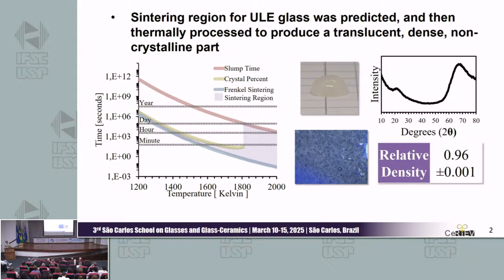The purple highlighted region shows where we have suitable sintering parameters. So at that time and temperature, you should get a translucent, densified, non-crystalline glass part. And we've done some testing on additively manufactured glasses using this model. On the right, you can see one of those samples. There is some opaqueness, but it is translucent. We have confirmed there's no crystallinity with XRD methods, and we have high relative densities compared to the glass system we were looking at. We do have some bubbling issues, but we're trying to iron those out right now.